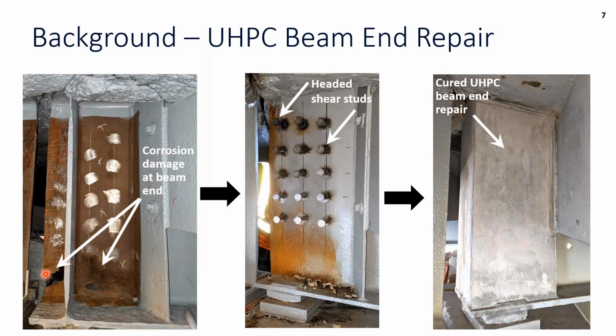We had full perforations in the web, close to full perforations in the bearing stiffener at both the top and the bottom. And the bridge, we cleaned all of the steel and then ended up going back and painting it. However, you can see the painting did not happen in the region that was going to be encased in the UHPC, because the UHPC itself provides protection. And then you can see the areas that are really well cleaned beneath those headed shear studs.